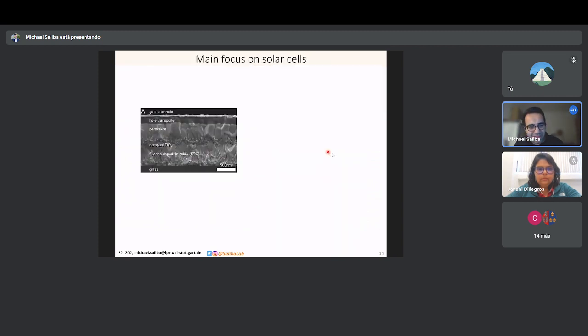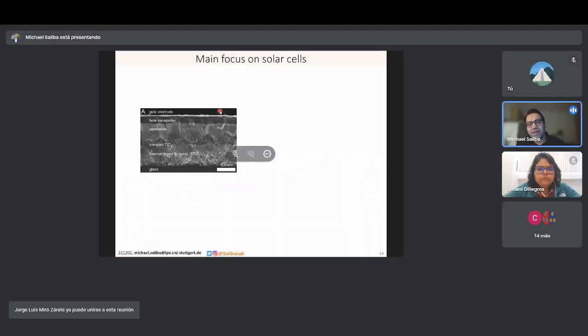So now the rest of the talk, the main focus will be on solar cells. Just to be super upfront about it as well, you see here, the perovskites are sandwiched between an electron transporting layer, which is fluorine-doped tin oxide with a compact layer, and a little bit of mesoporous TiO2, a remnant of the history from the dye-sensitized solar cells. And then the top layer is a hole transporter, commonly a small molecule like spiro-OMeTAD, but it can be other stuff as well, like copper thiocyanate and so on. And then, of course, you need to contact it, in this case, with a metal electrode.